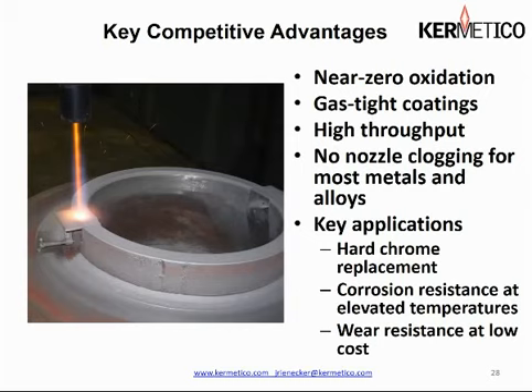We have no nozzle clogging whatsoever for virtually everything we spray. There's a couple of problematic materials, but that's cleaned up by adding grit. The key applications we've been involved in here at the headquarters spray shop, which is really our R&D lab, we do a lot of hard chrome replacement, especially for hydraulic rods in marine environments where corrosion is a problem, because everybody knows hard chrome plate is porous. We also do very well with corrosion resistance at elevated temperatures with chrome carbide and other materials like that.